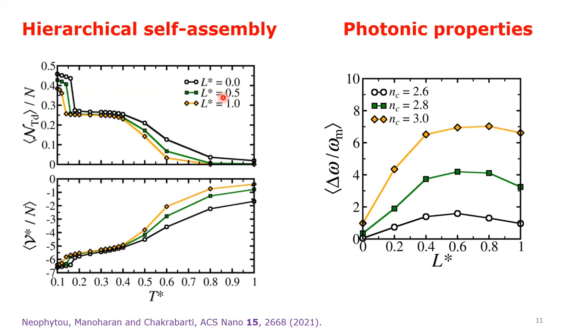and the band gaps spectrally overlap. We calculated the photonic band structures for randomly stacked structures. On average, we find that the photonic band gap survives and it can be maximized with an optimal choice of L star.